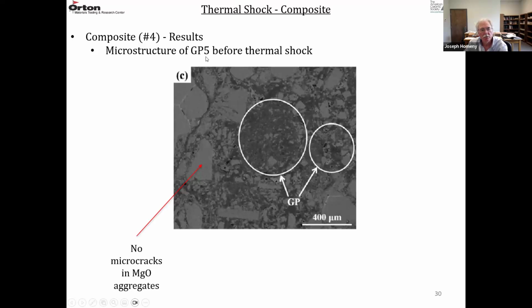This is GP5 before thermal shock, and they're outlining 2 areas of the pellets. And again, there are no micro cracks in the MgO grains. You can see some of the impurity here along the grain boundary between 3 crystals. Here's some more impurity over here between this crystal and maybe 2 other crystals.